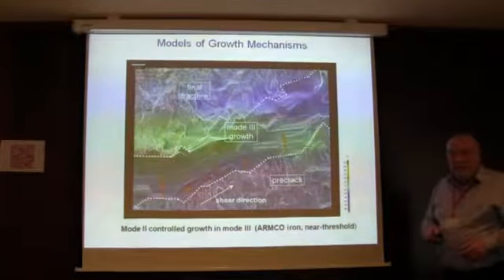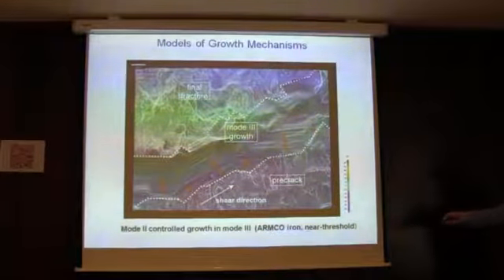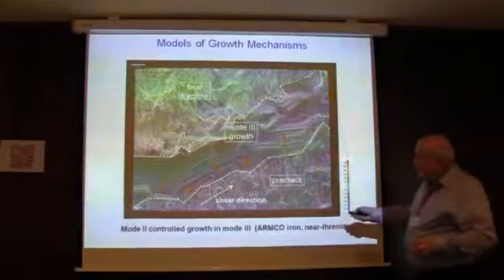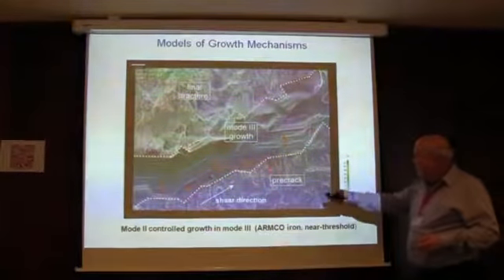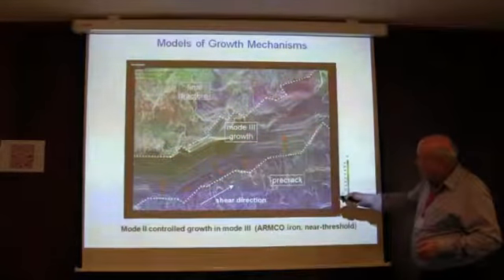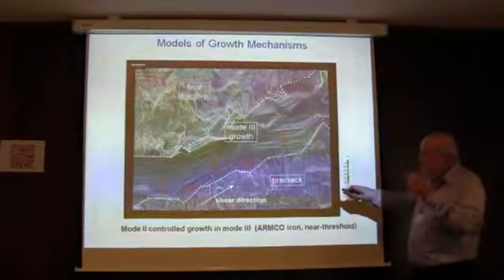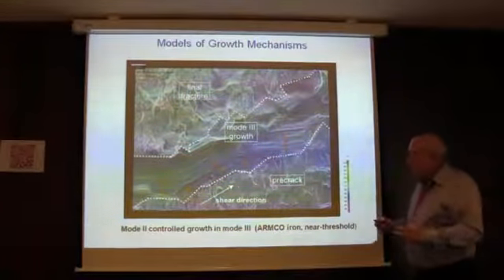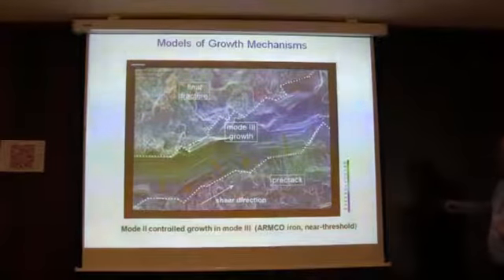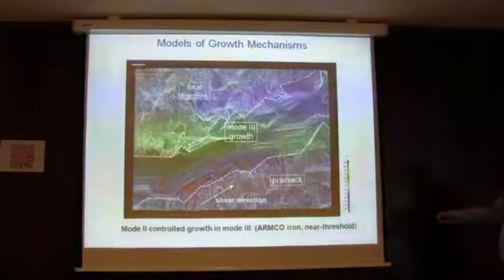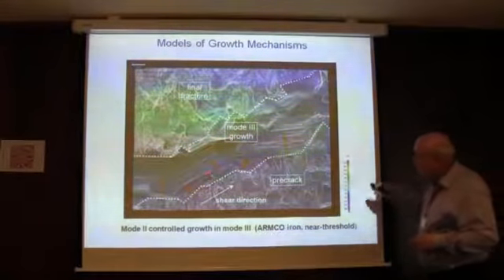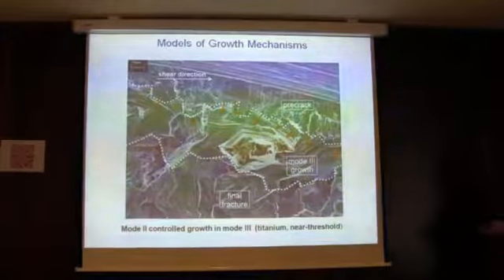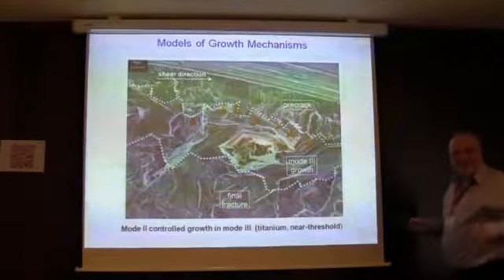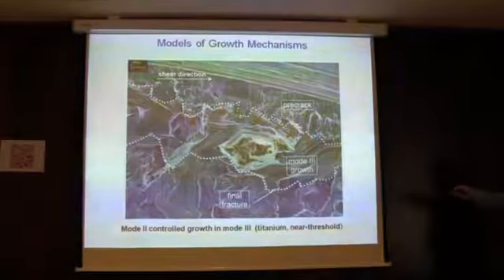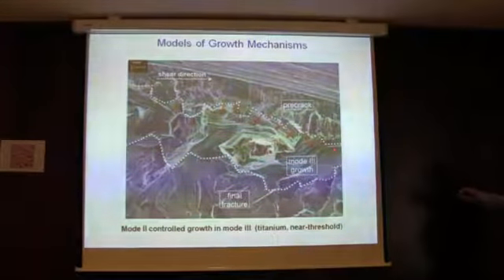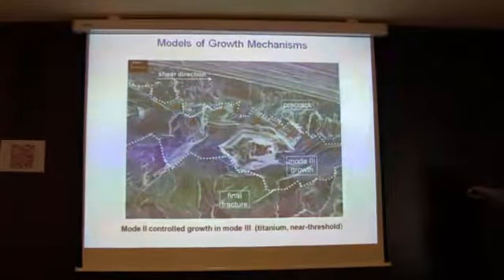And now you can see here that really, for example in iron, near threshold propagation, this is the pre-crack front, like this, and you can see the propagation of the cracks like this. So this is actually not pure mode 2, but a significant mode 2 contribution from the crack front in the mode 3 case. This is the shear direction of the external mode. This is mode 3. The crack propagates like this. And this is the same case in titanium. This is a new picture, so that was not shown in the guide. This is titanium, and you see a pre-crack front like this, microscopically rough, and you see various kinds of crack propagation directions.